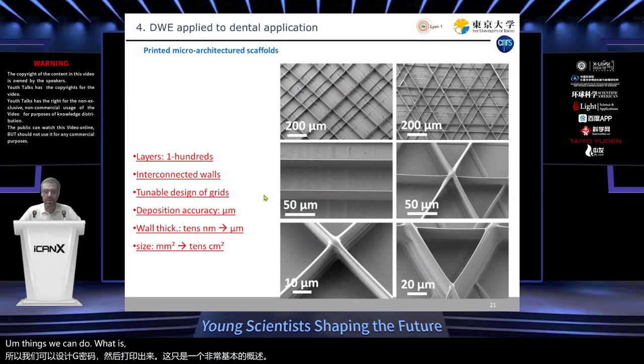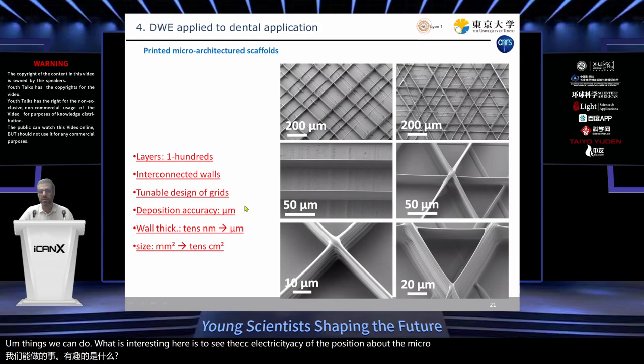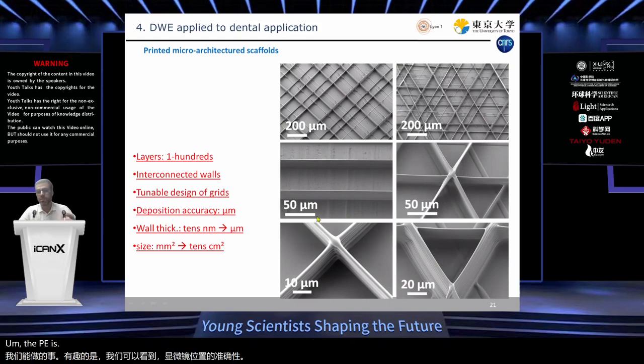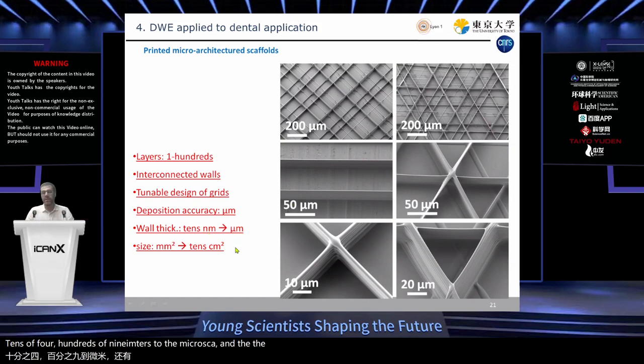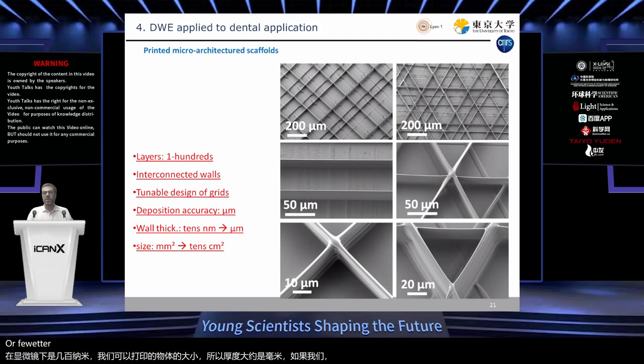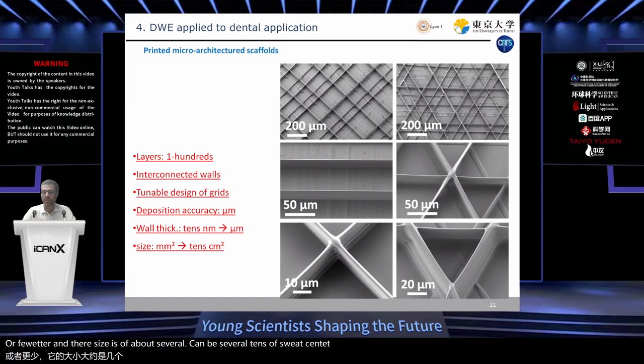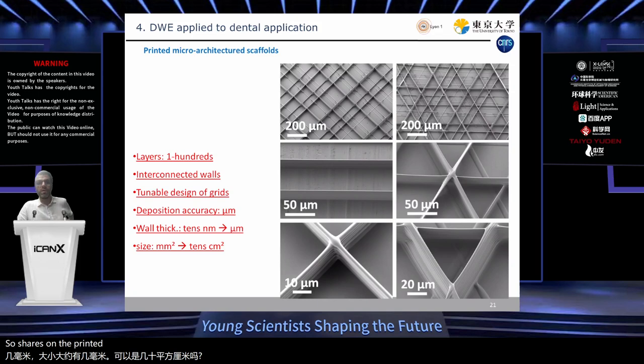What is interesting here is to see the accuracy of the deposition about the microscale, the thickness of the walls we can print from tens of hundreds of nanometers to the microscale, and the size of the objects we can print. So the thickness is of about the millimeter scale if we want, or a few millimeters, and the size is of about several tens of square centimeters. So here are the printed architectures.